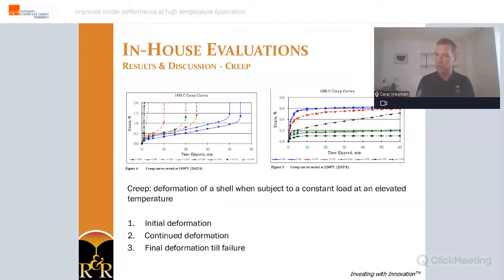And a creep test normally comprises three stages of deformation. And they're defined as follows. You've got the first initial stage where you see a rapid deformation. And this normally stops in a short period of time. Then in the second phase, you see a continued slow deformation. And it's typically with a very constant deformation rate. The third and final rapid deformation is immediately followed by a catastrophic failure of the sample.